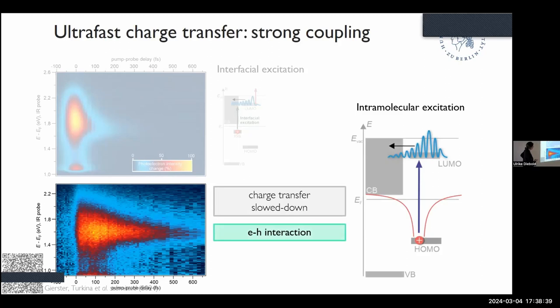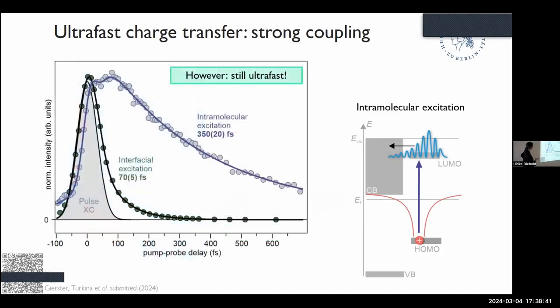But nevertheless, electron-hole interaction. Nevertheless, even 350 femtoseconds is still ultrafast. And this is still strong coupling. So the electron-hole interaction on the molecule can also not be the cause of the reduced charge separation in zinc oxide hybrid systems.